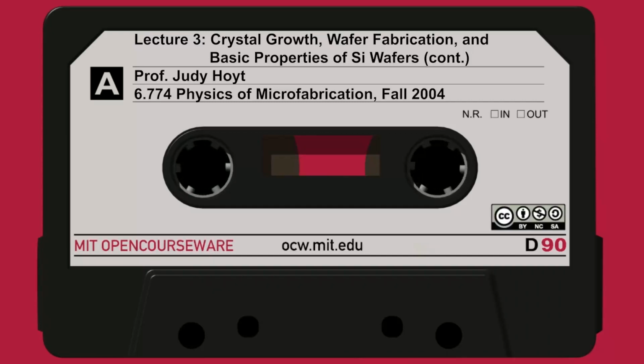But if we're intrinsic material and we look at all these levels, these are deep acceptors and deep donors. In this particular case, the Fermi level, which is right here at EI, is above the vacancy donor level, so it's above these guys. So these will not be ionized. And same thing here, the Fermi level is below these vacancy acceptor levels. It's down here. So these levels won't be ionized.